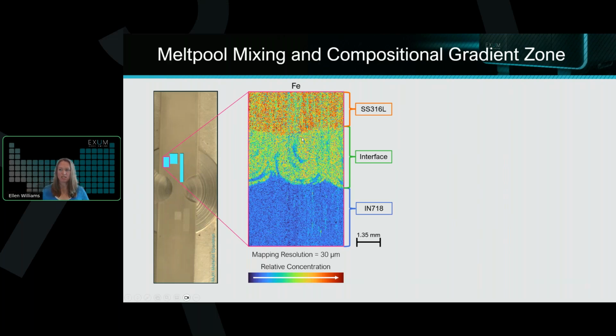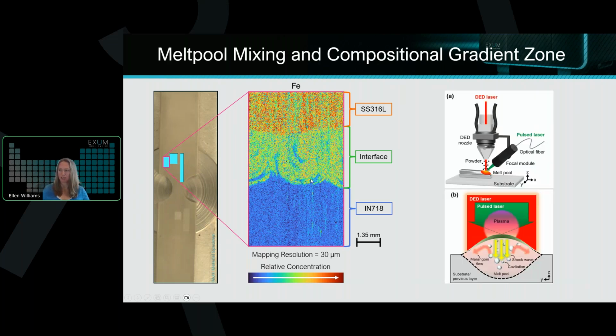And so what you see here is the size and shape matches the melt pool beads that were created as part of this DED printing process. And if you're not familiar with the DED process, you can see that in the diagram on the right here, where we have those melt pools with essentially a diameter and a size and shape consistent with the pulsed laser diameter. Because as we're creating a plasma, heating up the powder and melting it, we get this phenomenon that you see in the bottom here of this melt pool, that you can see this curved shape that we're identifying in the map, and then this Marangoni flow as well.